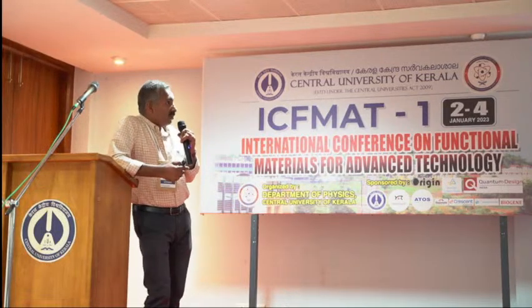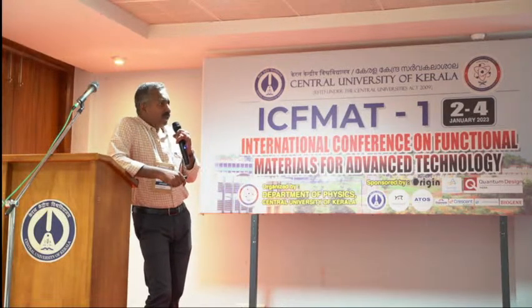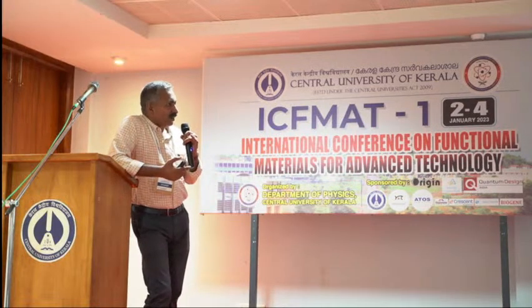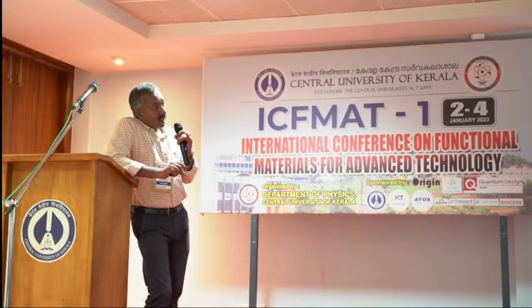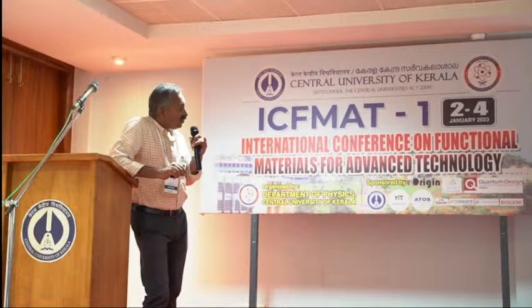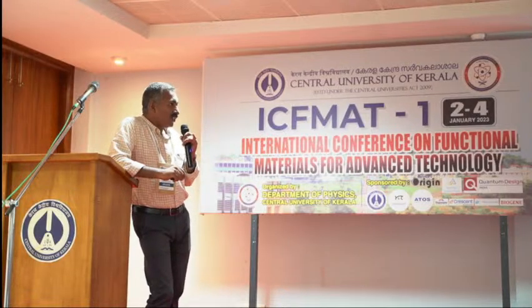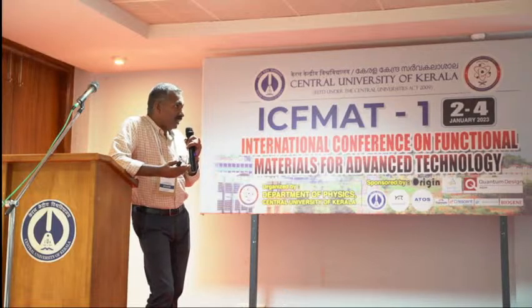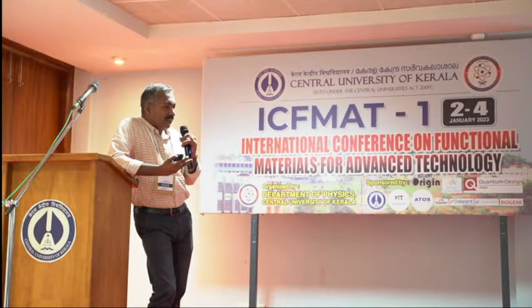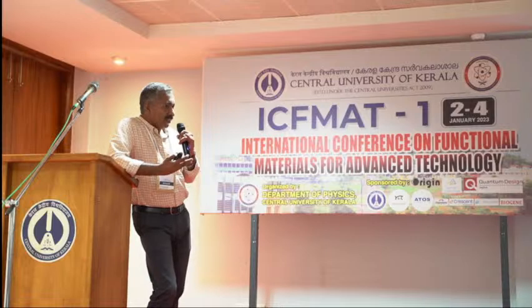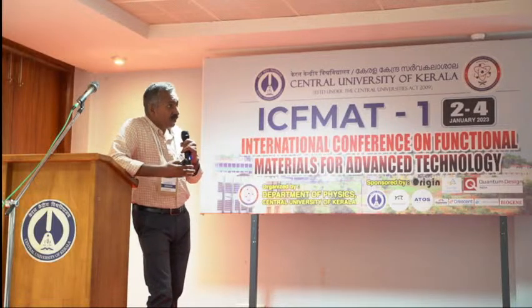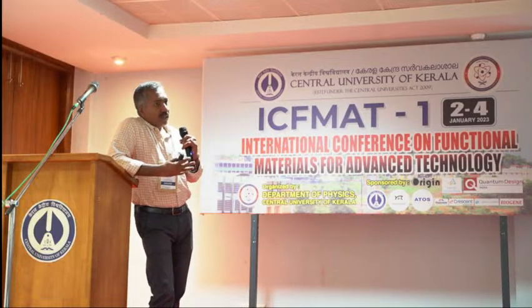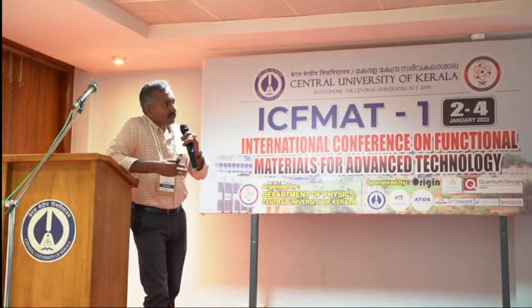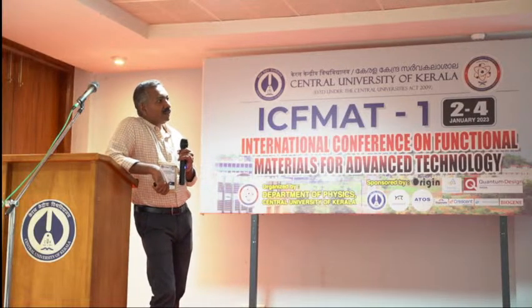An erbium doped fiber amplifier doesn't give you lots of power, but even that laser can be mode locked by means of a saturable absorber, which is made from a 2D material like MoS2, for example. So the intensity that you need in this particular case is much lower than the intensity that you need in the case of a normal, typical 3D material. Yes.